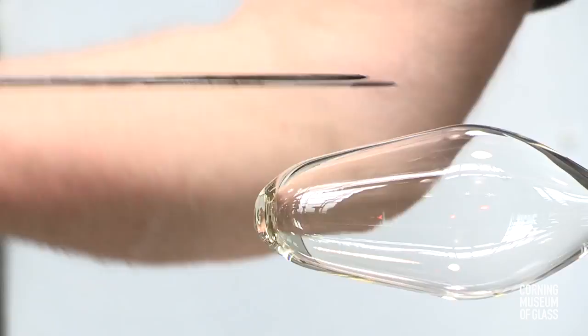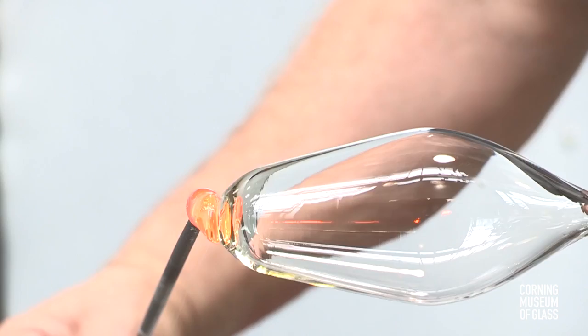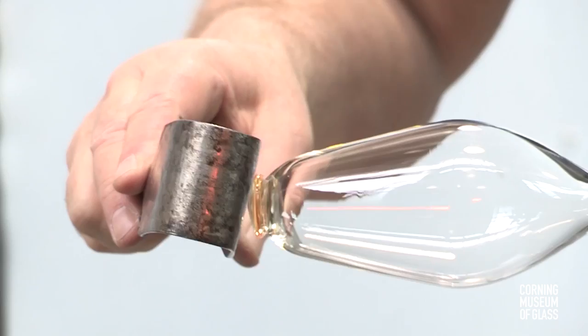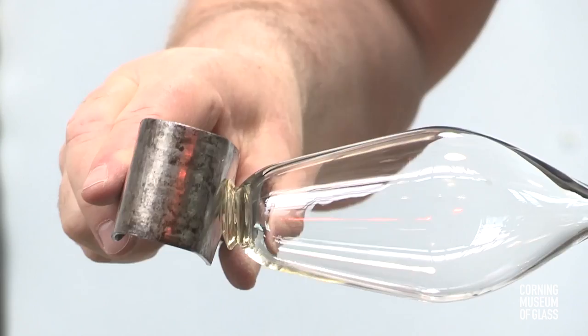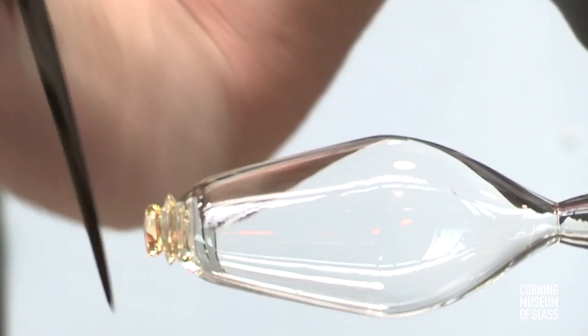Next begins the process of adding bits of glass and bubbles. The first thing is a tiny bit of glass added at the tip and tooled to become a merese — a decorative disc, somewhat sharp at its edges and conical at its face. Another bit of glass is added, cut free, and after a brief reheat, this is flattened and the constriction tooled and pulled slightly outward.